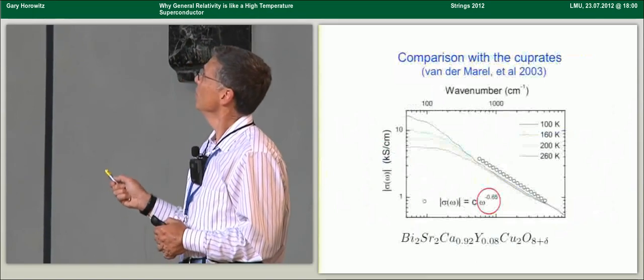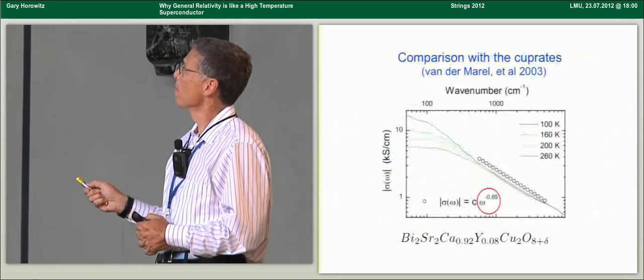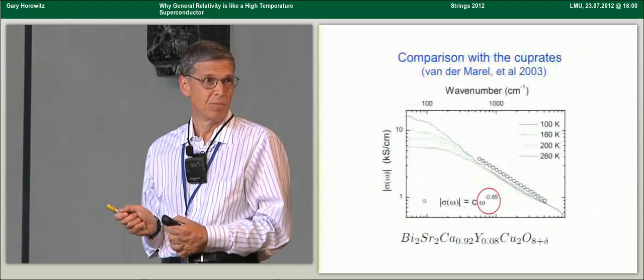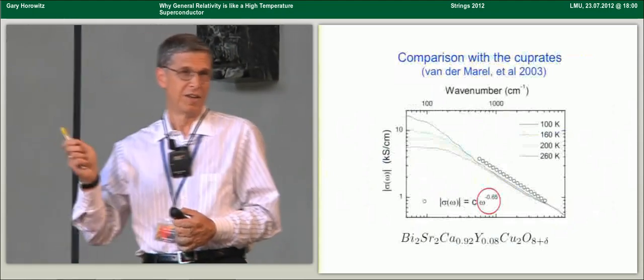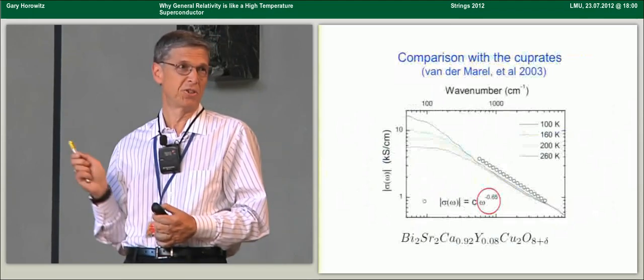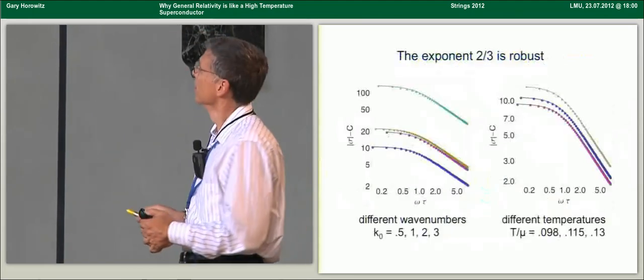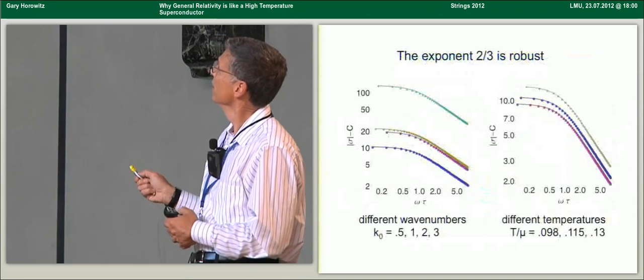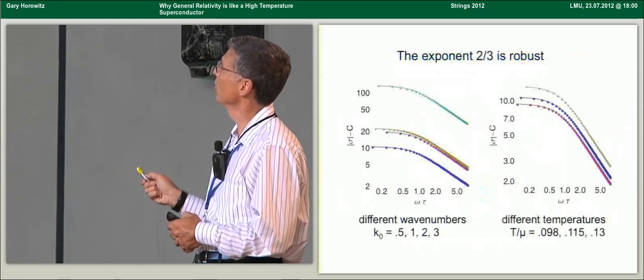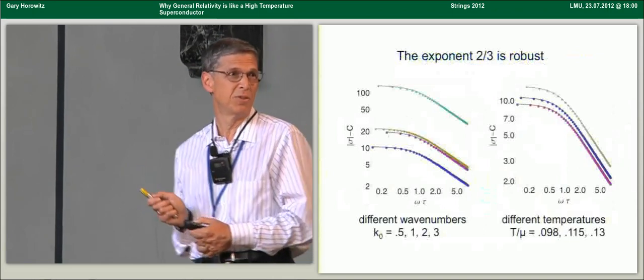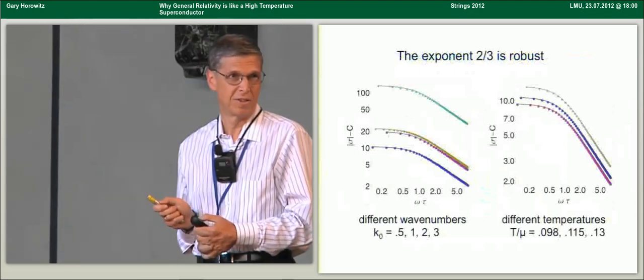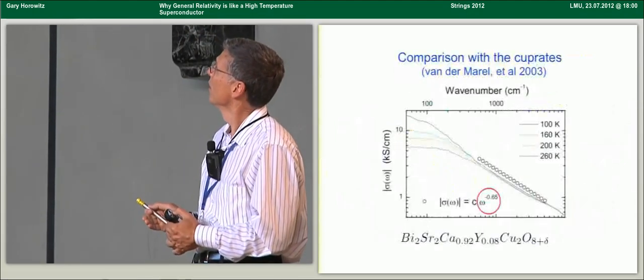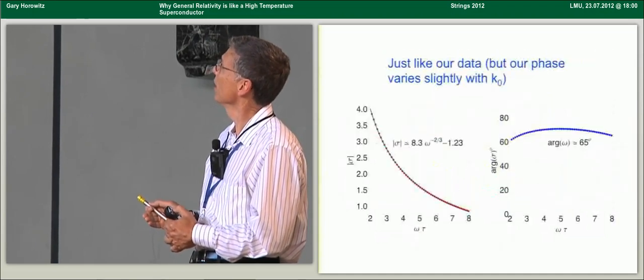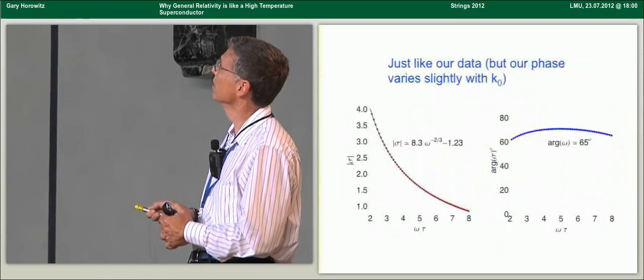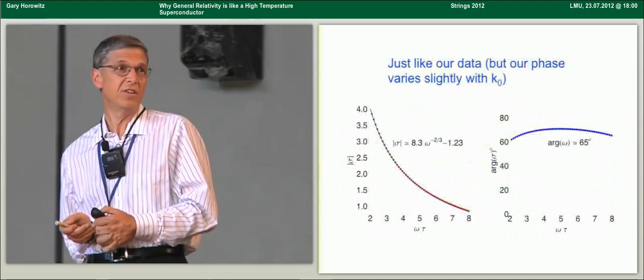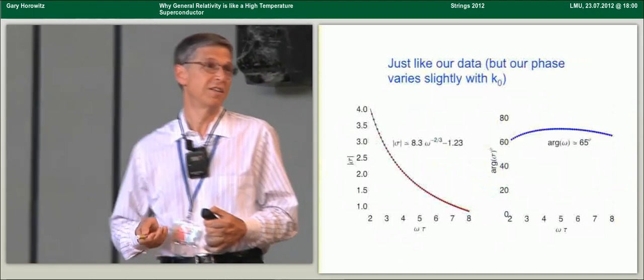And second of all, you see that when they vary their temperature, these curves are exactly the same, which means that the coefficient of the 1 over omega to the 2/3 is temperature independent. And if you go back and look at our data, here we vary the temperature and we do see a slight change, slight temperature dependence of our coefficient. So those are a couple of differences, but still the exponent is coming out right and the phase is looking pretty good. So the next thing you can ask is, what about the DC conductivity?